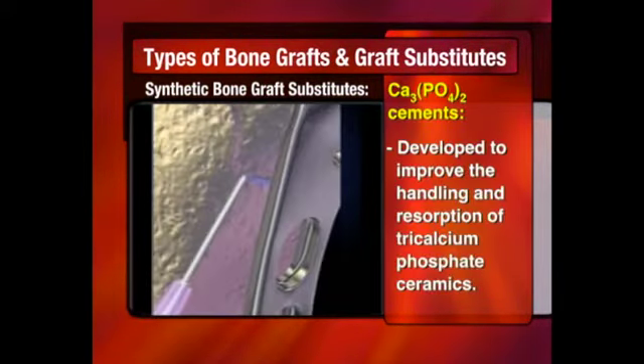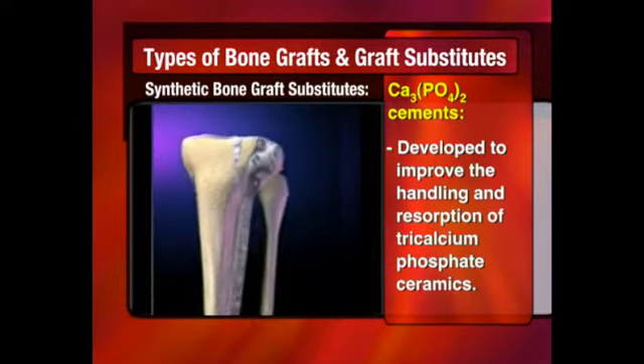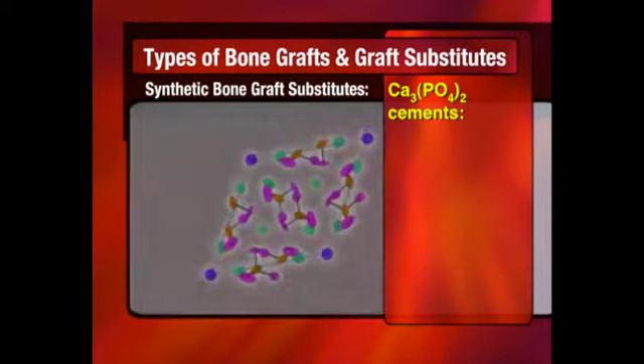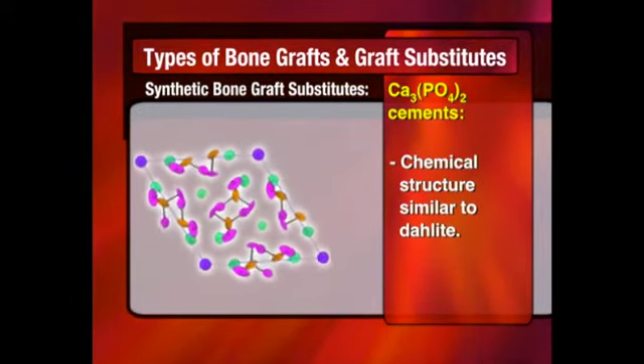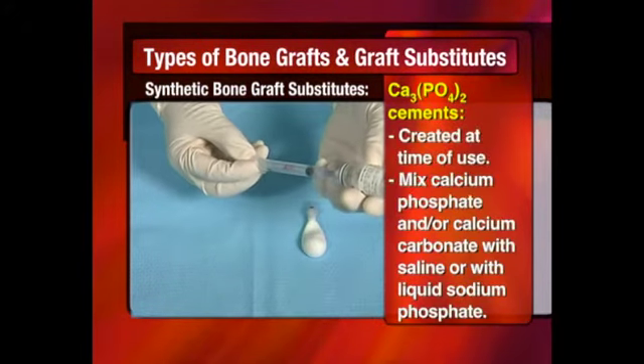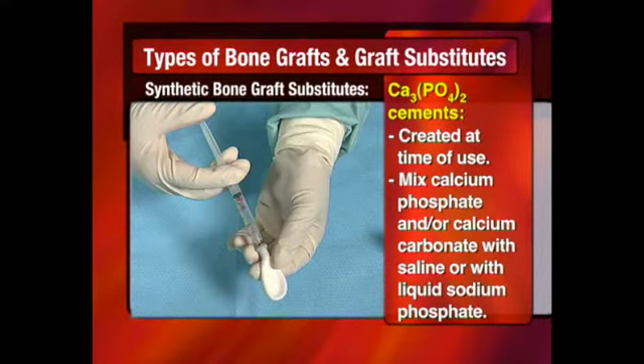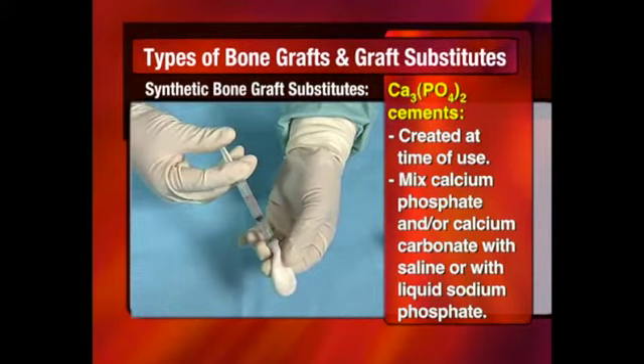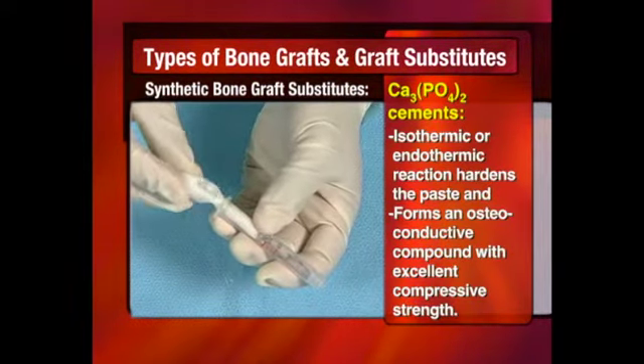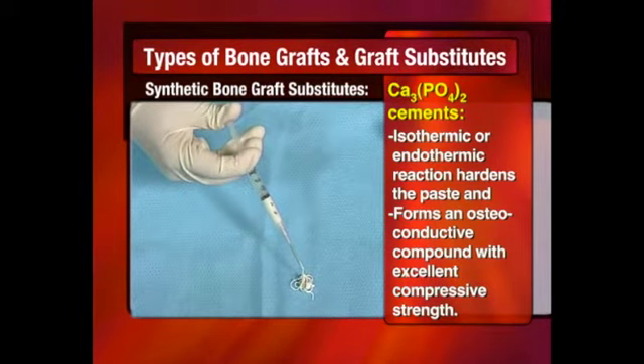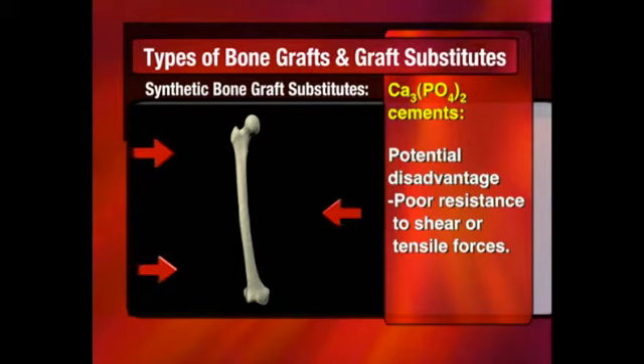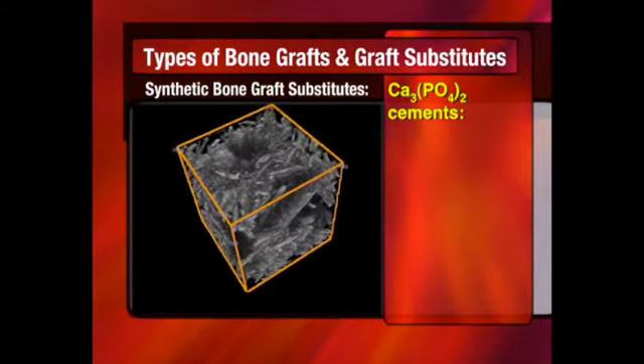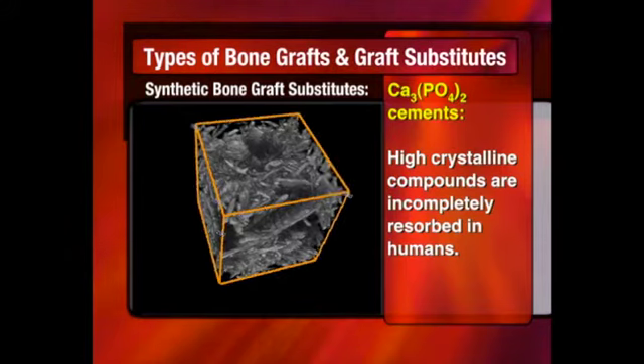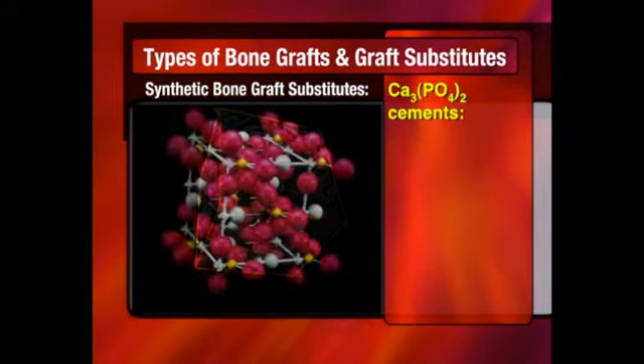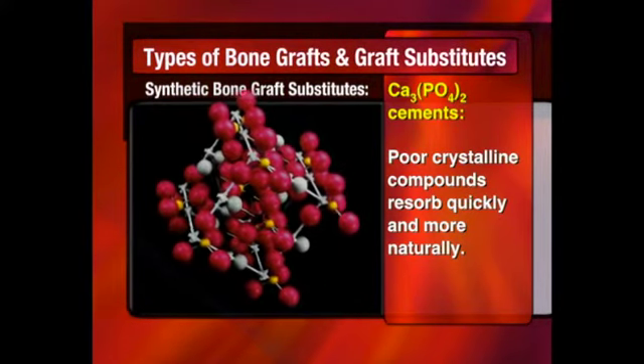Calcium phosphate cements were developed to improve the handling characteristics and resorption of the tricalcium phosphate ceramics. These compounds have a chemical structure similar to dahllite, the predominant mineral in bone. These materials are created at the time of use by mixing powdered calcium phosphate and/or calcium carbonate with liquid sodium phosphate or saline. The resulting paste hardens in an isothermic reaction and forms an osteoconductive compound with excellent compressive strength. A potential disadvantage of calcium phosphate cements is their poor resistance to shear or tensile forces. Early clinical experience with these compounds with high crystallinity has shown that they are incompletely resorbed in humans. Poorly crystalline calcium phosphates are known to resorb quickly and more naturally.